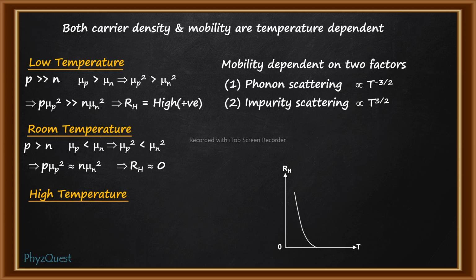As temperature is very high, due to a higher amount of thermal energy, a large number of covalent bonds will break, releasing a large number of free electrons and holes. At this stage, the hole carrier concentration is almost similar to the electron carrier concentration. Therefore, p will be almost of the order of n. Now at high temperature, intrinsic charge carriers are much higher, but the scattering will also be higher, due to which mobility will reduce. Mind you that here the lattice contribution of mobility will still be dominant. Here again electron mobility is higher than the hole mobility in general. Therefore here again mu p will be less than mu n.